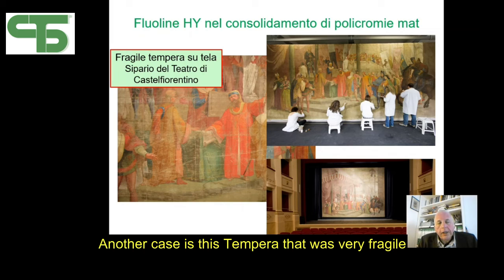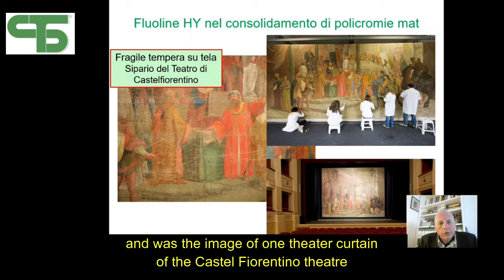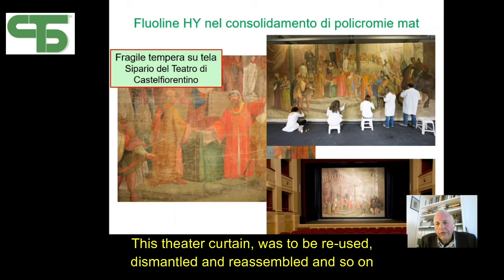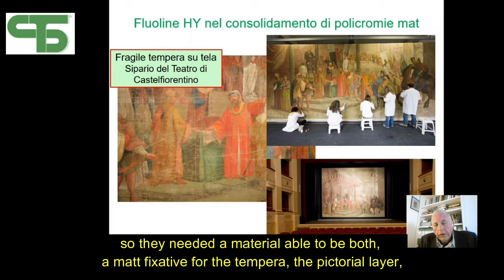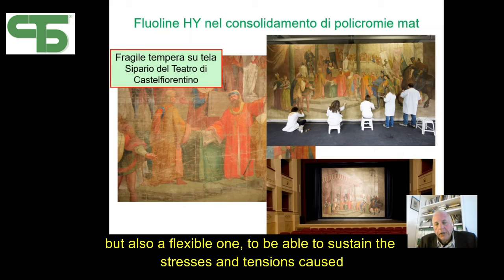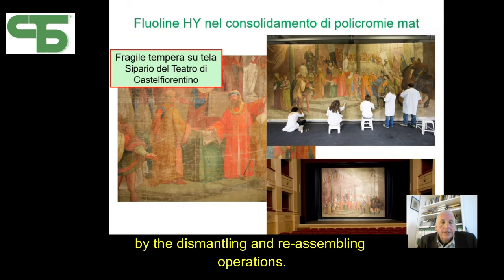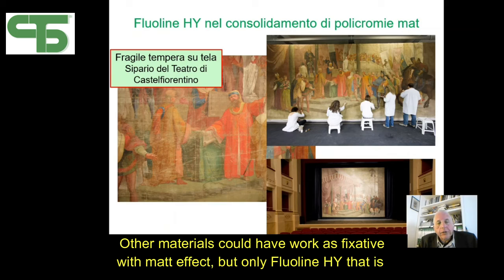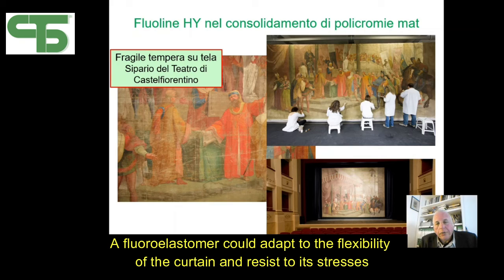Another case is this tempera that was very fragile, and it was the image of one theater curtain at the Castelfiorentino theater. This theater curtain was to be reused, dismantled, reassembled, and so on. So they needed a material able to be both a matte fixative for the tempera and the pictorial layer, but also a flexible one to be able to sustain the stresses and the tensions caused by dismantling and reassembling operations. Other materials could have worked as a fixative with a matte effect, but only Fluoline HY, that is a fluoroelastomer, could adapt to the flexibility of the curtain and resist its stresses.